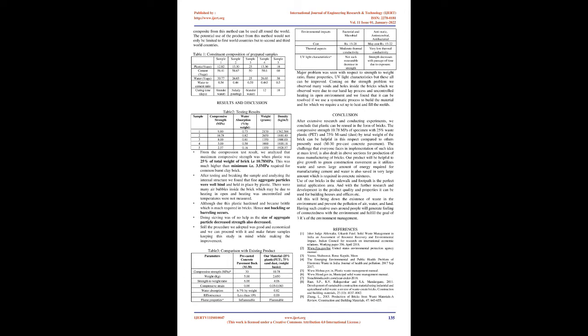This method will not only consume plastic in large quantities but will also reduce the need for cement in cast structures such as pavers. This reduction in cement use will decrease the pollution arising from the process of making cement. Although this method is very efficient at reducing pollution, it comes with the drawback of producing pollution in the melting process of the plastic. Some measures that can be used to minimize the pollution from the gases produced by this method are implementing air filtration systems to capture as much toxic gas and aerial pollutants as the plastic is melted.